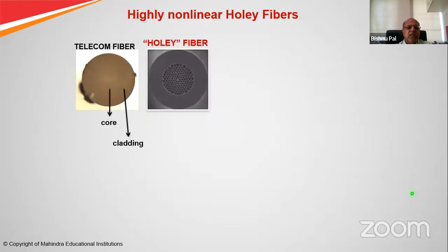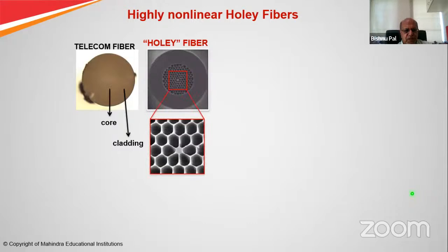So let us consider a highly nonlinear holey fiber. Holey fibers, also called microstructure fibers, are called that because there are a lot of holes in the microstructure cladding. So we consider a core which is surrounded by so many holes. You can see there are bigger holes, so a large air fraction is sitting here, with a very small core of high index. This will give a high numerical aperture fiber and a very strong nonlinear effect.